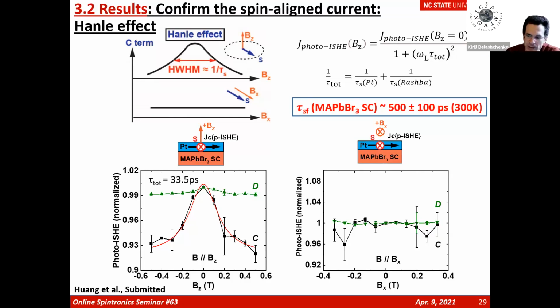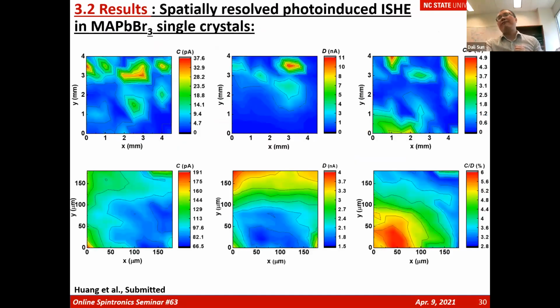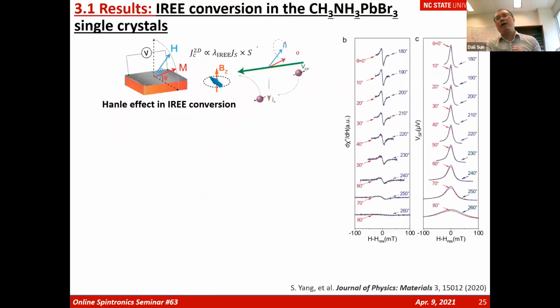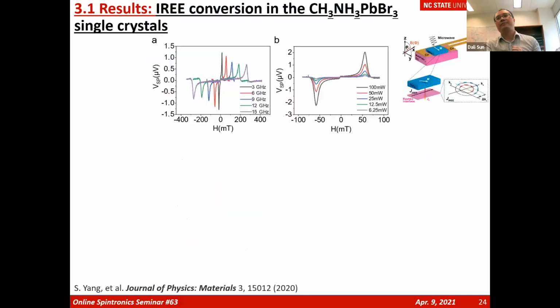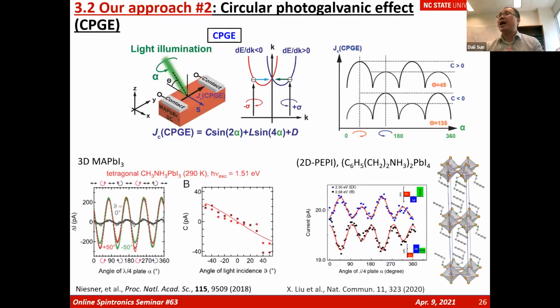The fact that you have it in spots, as you showed, is probably not a good thing for transport measurements. You want a fairly uniform device, right? Yes. Is there an idea on how to get there? Of course. The whole work here is to address the main debate of why some people observed it and some did not, which is due to the local Rashba state in cubic MAPbBr3. Actually, we have another material that we have demonstrated before, a two-dimensional hybrid perovskite. It is supposed to form a uniform surface state, even a bulk Rashba state, because it inherently possesses Rashba splitting without local distributions.